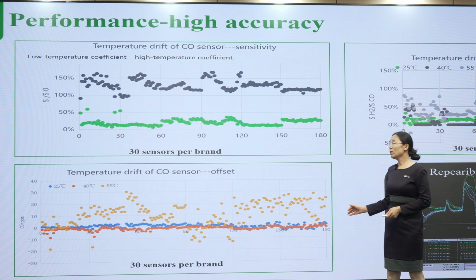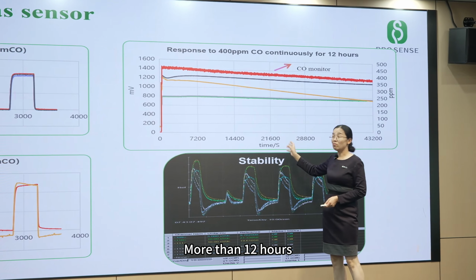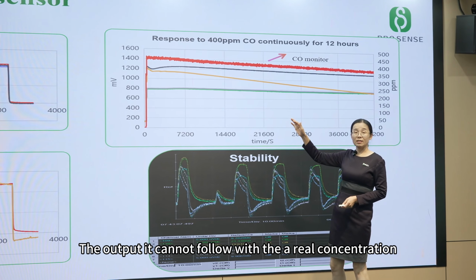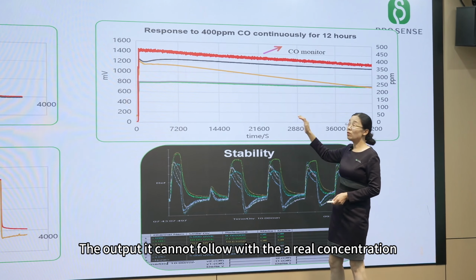And also the repeatability of the sensor is very important. Please check the repeatability of your sensor. This one has a good repeatability, and for this one, the two sensors have different responses when we do the repeatability test. And this one is the polarization of the sensor. When there is carbon monoxide for a very long time, more than 12 hours, the output cannot follow the real concentration. So all of this will affect the accuracy of the sensor.